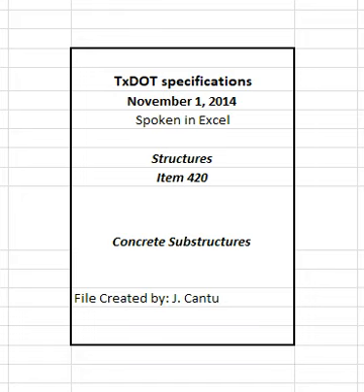4.10.2.1 Blankets. Keep the concrete continuously wet by maintaining wet cotton or burlap mats in direct contact with the concrete for the required curing time. Weight the mats adequately to provide continuous contact with all concrete. Cover surfaces that cannot be cured by direct contact with mats, forming an enclosure well anchored to the forms or ground so outside air cannot enter the enclosure. Provide sufficient moisture inside the enclosure to keep all surfaces of the concrete wet.